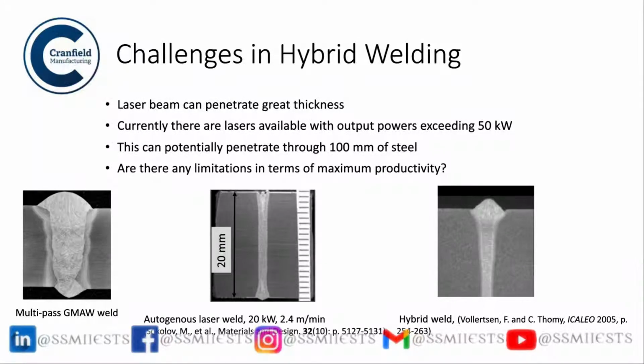So you can have a filler metal deposited. However, the point is it is not only deposition that is good, but the filler metal needs to penetrate. So practically you need to understand how the two power sources will respond or will interact with each other in order to push the filler wire through to the bottom.